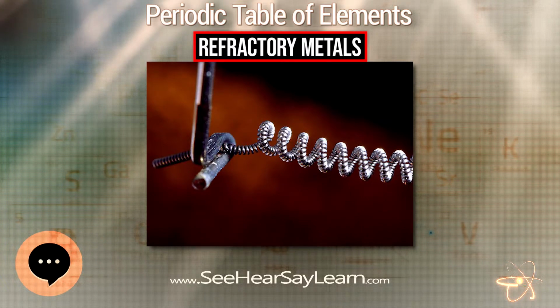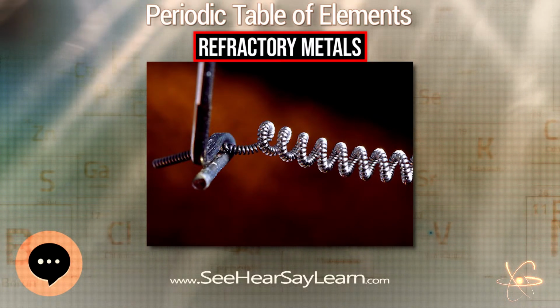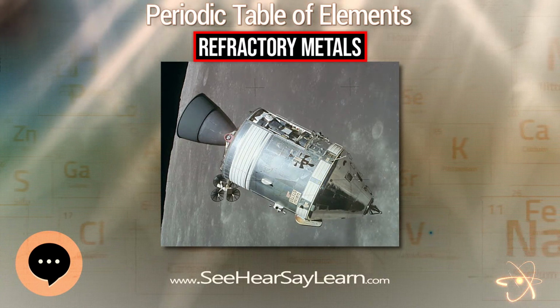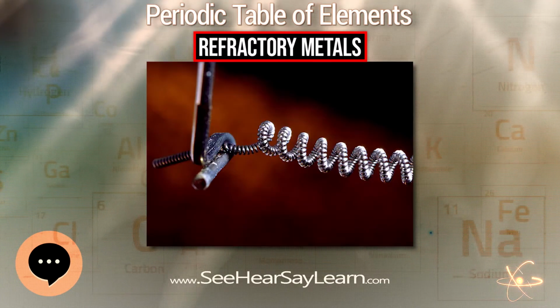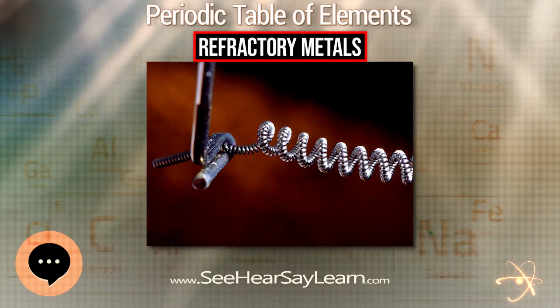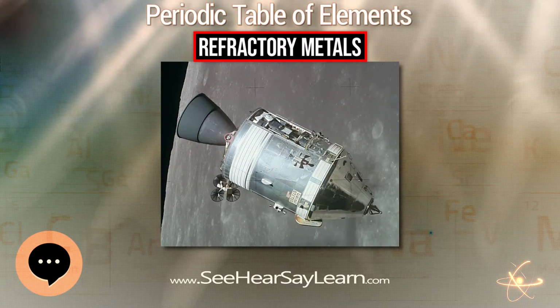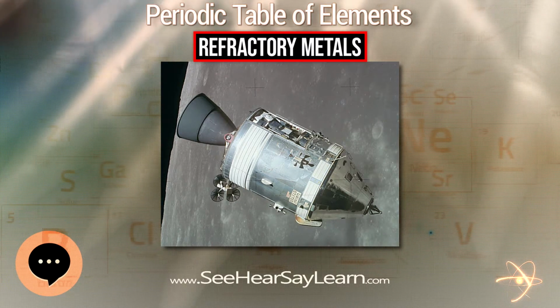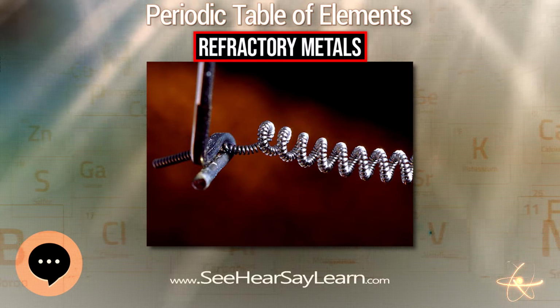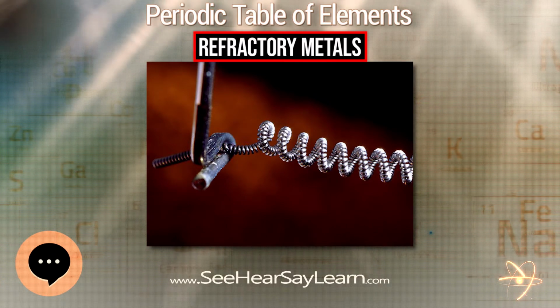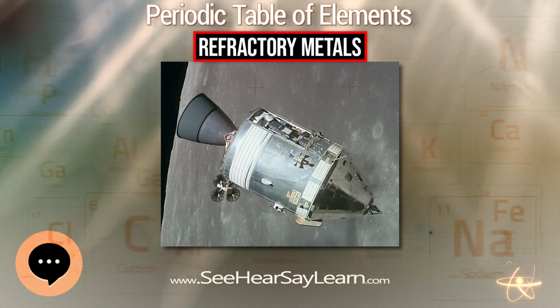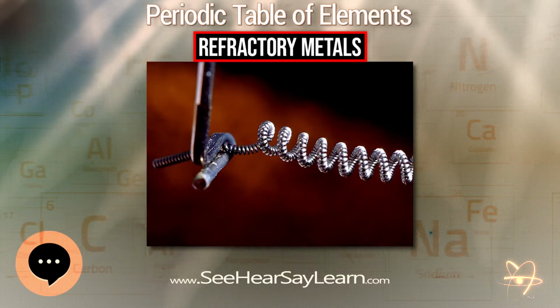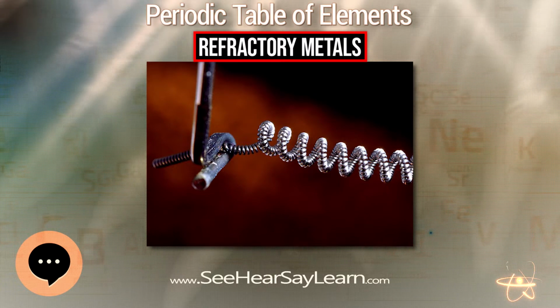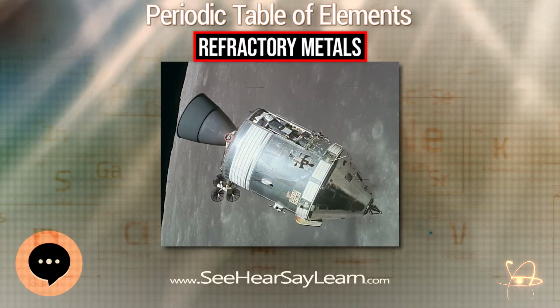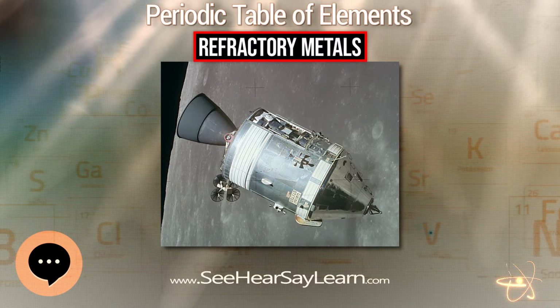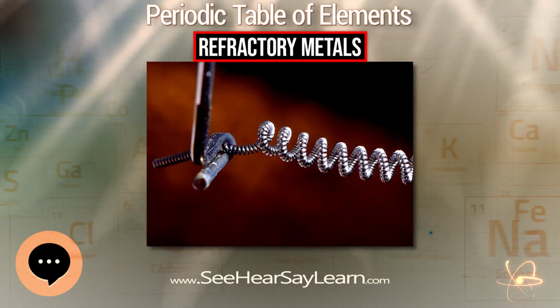Interactions with the environment can significantly influence their high-temperature creep strength. Application of these metals requires a protective atmosphere or coating. The refractory metal alloys of molybdenum, niobium, tantalum, and tungsten have been applied to space nuclear power systems. These systems were designed to operate at temperatures from 1350 K to approximately 1900 K. An environment must not interact with the material in question. Liquid alkali metals as the heat transfer fluids are used, as well as the ultra-high vacuum. The high temperature creep strain of alloys must be limited for them to be used. The creep strain should not exceed 1–2%.